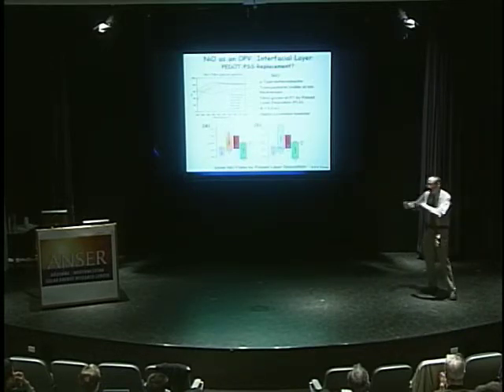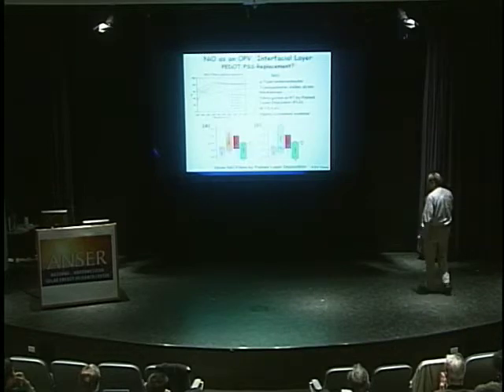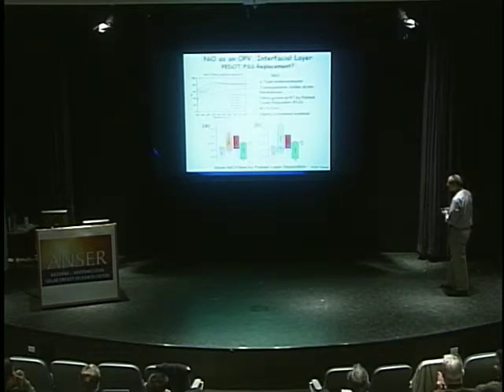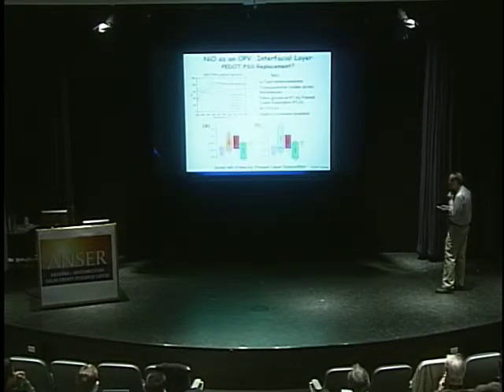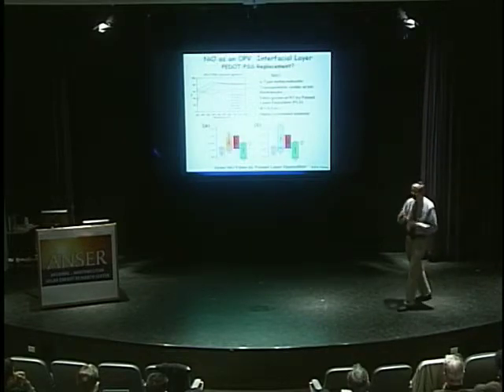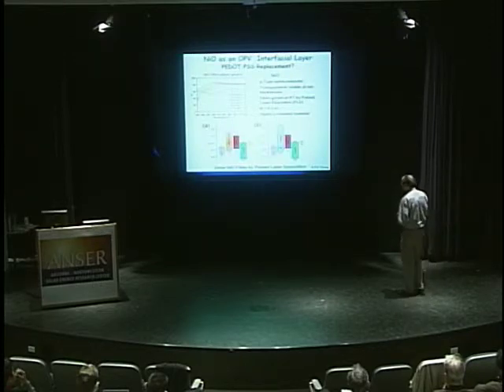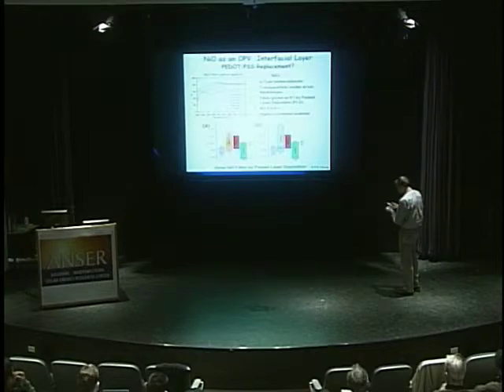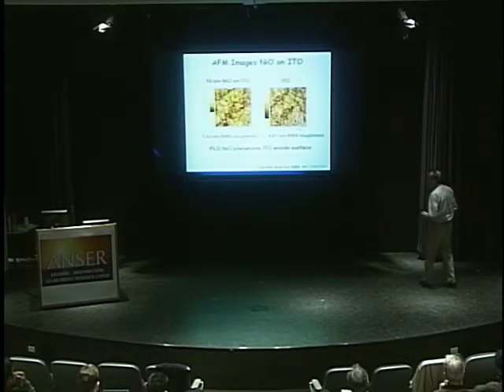And that's something aside from what the discussion is this afternoon. But the other thing is, if you match up the energy levels, nickel oxide matches up, the Fermi level matches up very nicely. We should have a relatively good ohmic contact, and the conduction band is very, very high. All of those say it's going to be hard to get electrons leaking back to the ITO from our active layer. And so these are different film thicknesses that we grew. And let's make some cells.